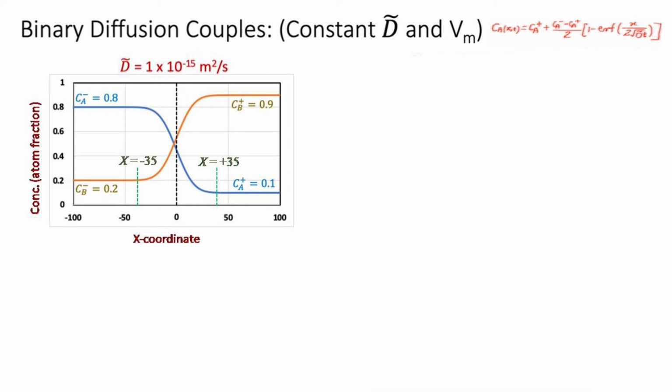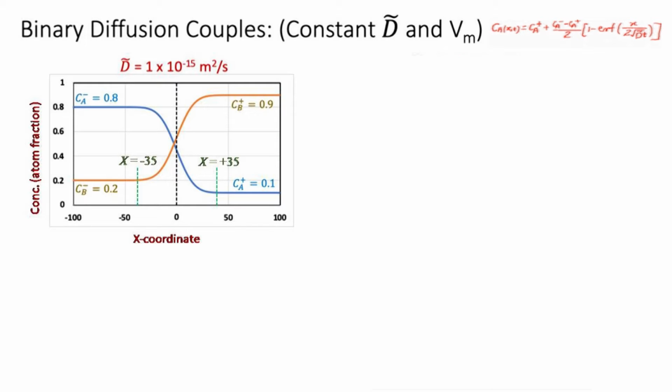So, we are considering interdiffusion here, and the interdiffusion coefficient is usually denoted by this symbol, tilde on top of d. So, d tilde is the binary interdiffusion coefficient of the system that we are considering here. We have derived this equation and it has an error function type of solution, and this is the kind of profile that develops in a diffusion couple, right.